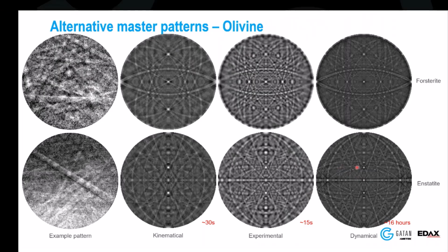And here we can see the dynamical simulation versus the actual information that we have in the patterns. There are quite some differences. And these differences are caused by the actual system itself that we're not really accounting for, like phosphor screen blooming, or minor changes in your materials. You can see that things like this little zone axis here look and behave much differently from your actual experimental data. So these look pretty close together, but if I can use this experimental information, it better matches what I'm actually collecting, which makes me start from a better point.